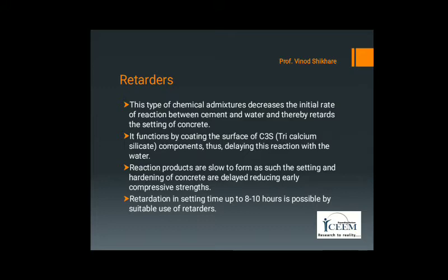Sometimes at that depth, stratified or porous rock strata may also require to be grouted to prevent the entry of gas or oil into some other strata of rock. For all these works, cement grout is required to be in mobile condition for about 3 to 4 hours, even at high temperature, without getting set. Use of retarding agent is often used for such type of requirement.